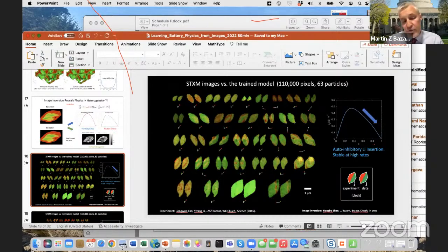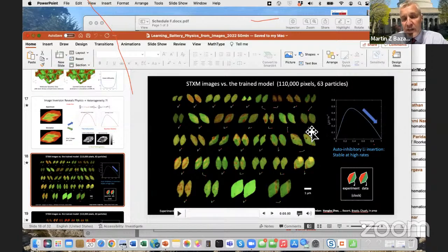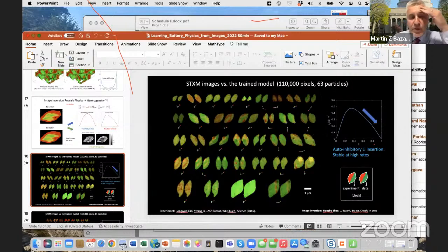Now I can show you other examples of this kind of approach, and we don't always get it to look so perfect. And even for this data, we did many other things with this. We also found that we could learn the model reasonably well, even without doing any of the spatial stuff, and simply knowing only something that was measured in the original experiments, which they call a uniformity coefficient. So it's basically how uniform the concentration is, some statistical measure, like a variance. If we know the uniformity versus time, and